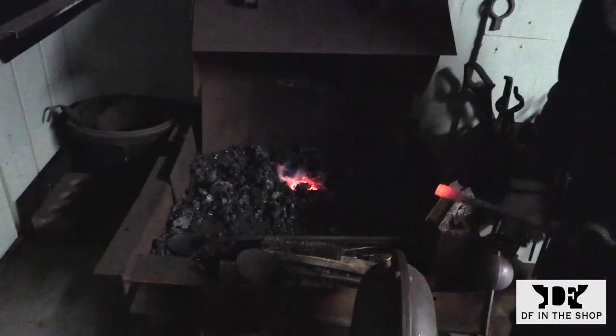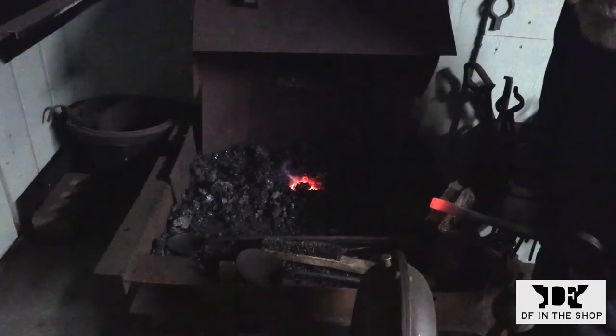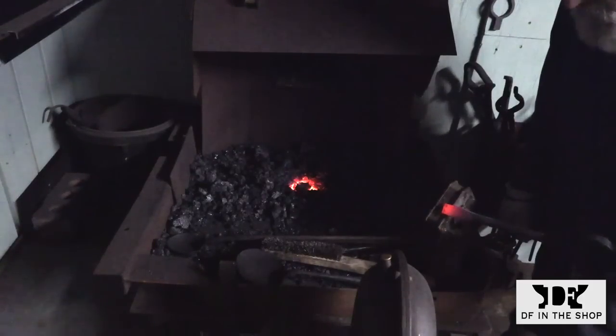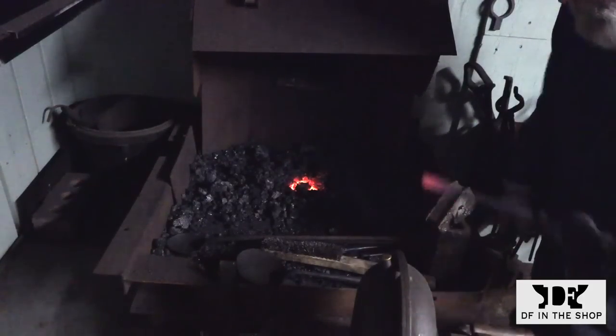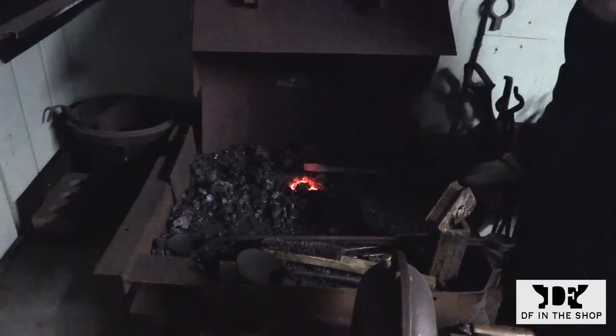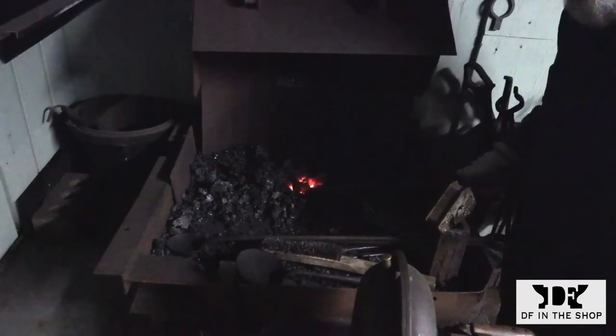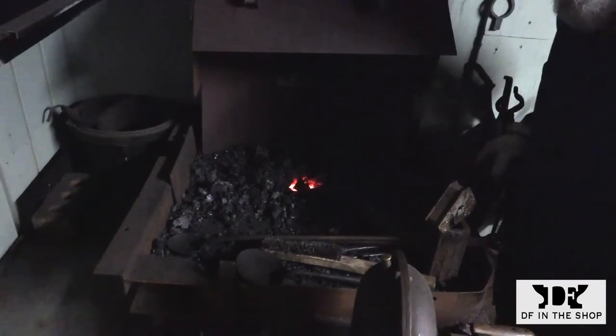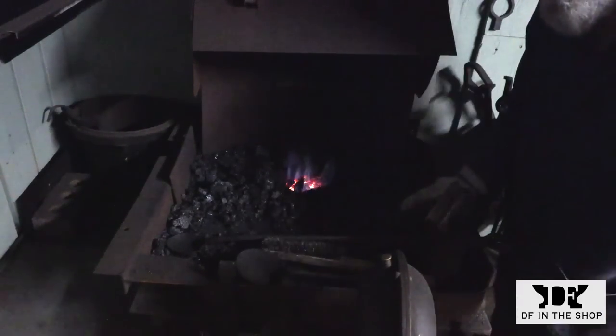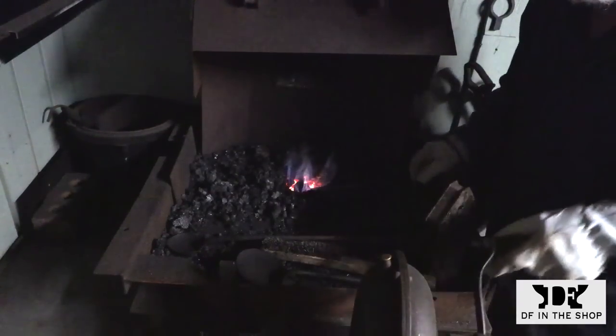Here you can see that I've heated the bar up quite a bit more, and there's a very noticeable difference in the color range, and it's still non-magnetic. So this is probably very similar to the first sample that I did at the higher light level, and it barely showed up as being red. And here we can see that it's really well above the critical temperature. But I'm going to keep going just to make a point.